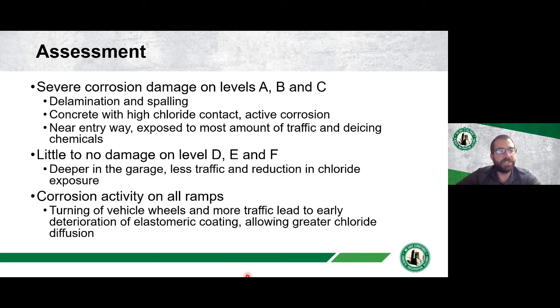So based on the condition assessment, we identified that levels A, B, and C were severely corroding. They had delamination and spalling. Concrete had high chloride content and active corrosion.